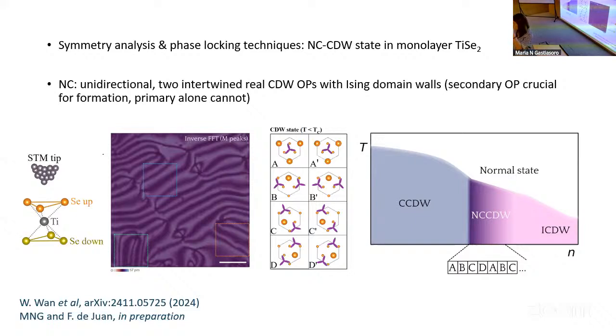So if you are at high temperature, you get only Bragg peaks, that G, and if you look at the M points, there is nothing. And when you go through the transition into the ordered state with the charge density wave, they will give contribution to those points and harmonics. So M plus G, M plus 2G, and so on. And if you want to know about that part of the electronic mumbo jumbo and filter it through all the rest, you look at those peaks. So those are the ones that have to do with the new order, which in the high symmetry phase are absent.